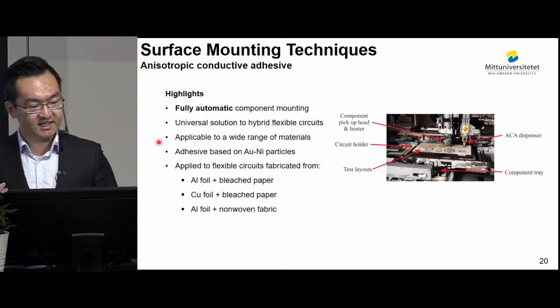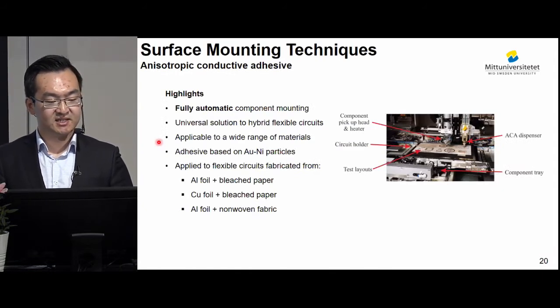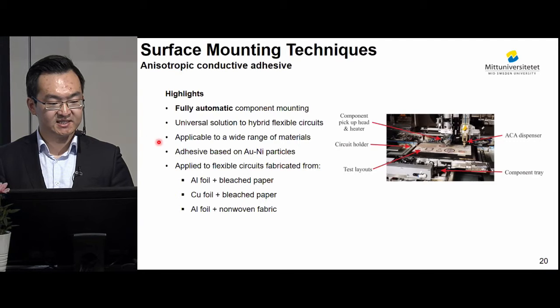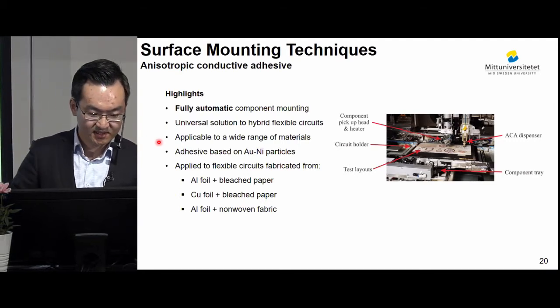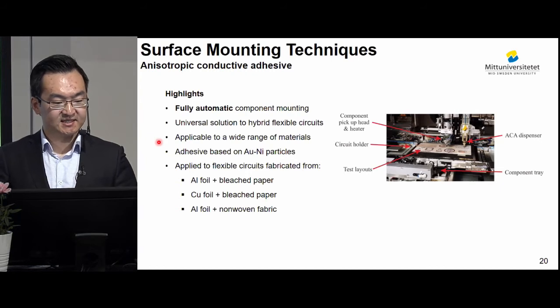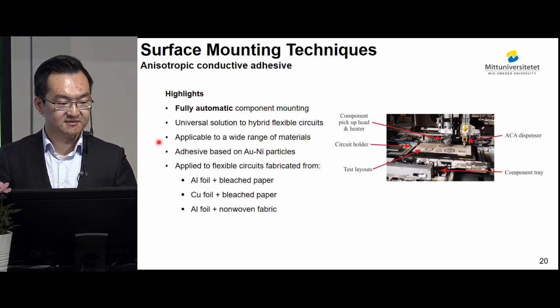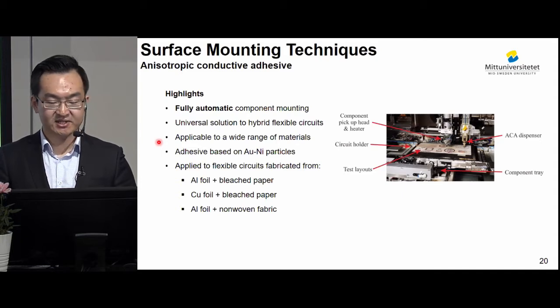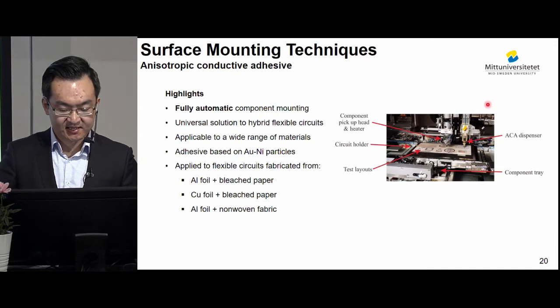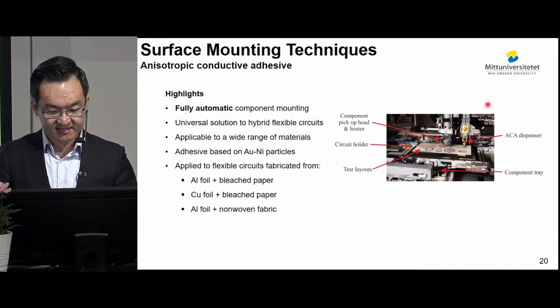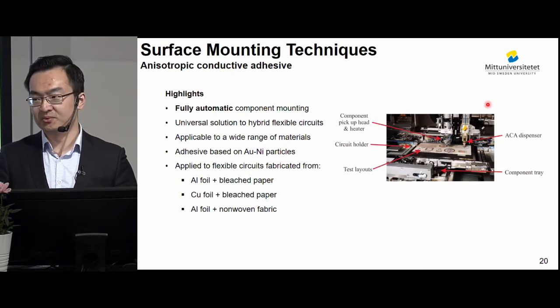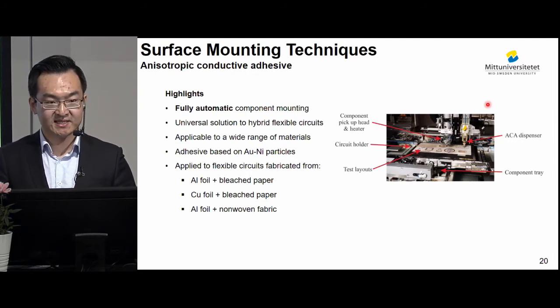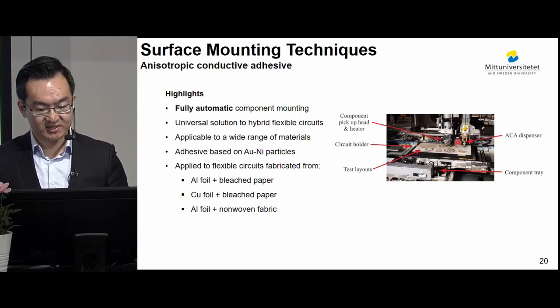The third surface mounting technique is an anisotropic conductive adhesive. I would like to highlight this technique because it is a fully automatic component mounting process. And the same as isotropic conductive adhesive, it is a universal solution to hybrid flexible circuits, and it can be applied to a wide range of materials. This photo was taken at one of our partner organizations when we were mounting components using an automatic component mounting machine. And this photo is what's inside of this machine.